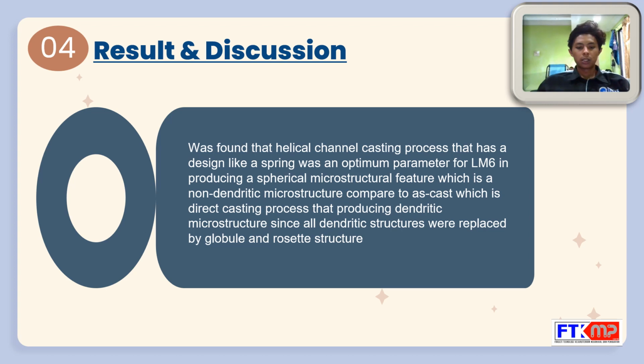The smaller globular size of the Al microstructure obtained in the helical channel sample improves its hardness property as compared to direct casting. Moreover, the stress value of helical casting aluminium alloy was increased compared to direct casting due to homogeneous formation of Al phase in the sample.